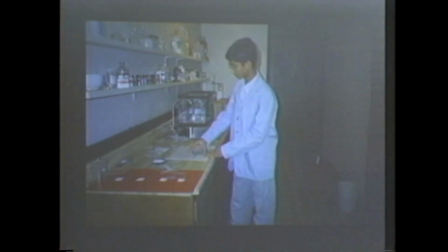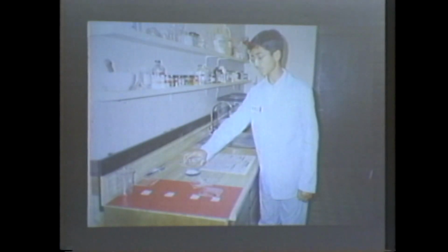I generated static by rubbing the plates against daily newspapers that had been conditioned at 65% relative humidity inside the humidity-controlled room for 48 hours. As shown here, I used 15 medium-pressure, 12-inch strokes for each sample. The samples were immediately held over a shallow dish containing ash, and the extent of ash pickup was noted. The samples were rated on a scale of 0 to 4, with 0 being no static buildup or no ash pickup, and 4 being the heavy static buildup characteristic of untreated plexiglass.